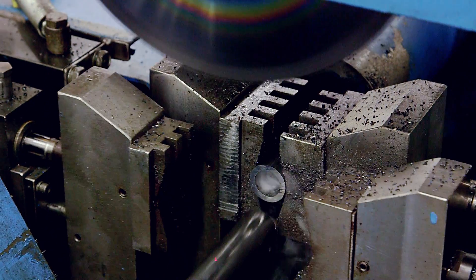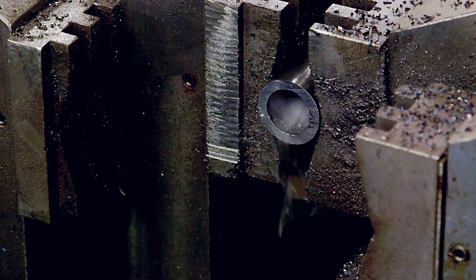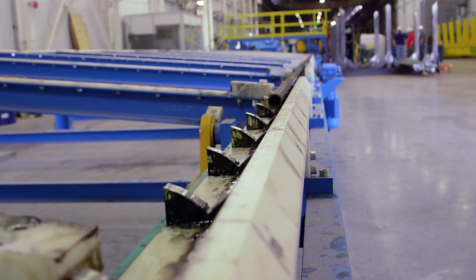As a result of the pilgering process, the larger diameter shell is reduced to a smaller diameter tubing. This smaller diameter tubing is therefore elongated to much greater lengths. We can take a two and three-eighths inch diameter shell that is just over 18 feet long and reduce it to a one inch by 0.091 inch wall that is over 122 feet long.